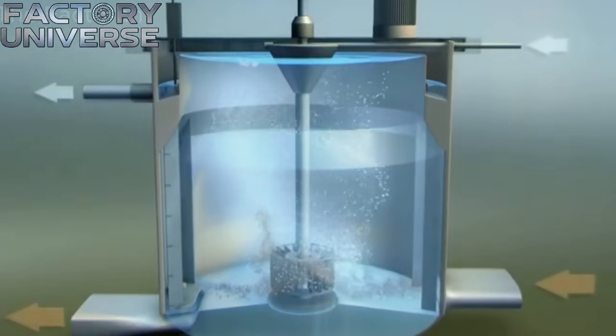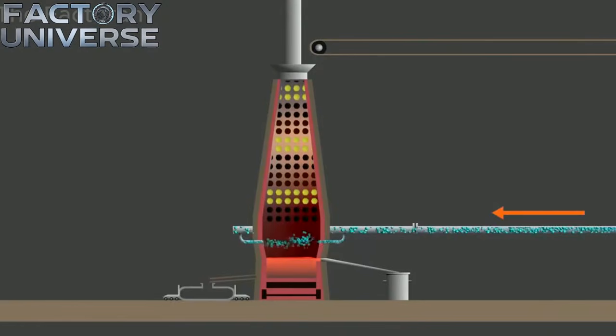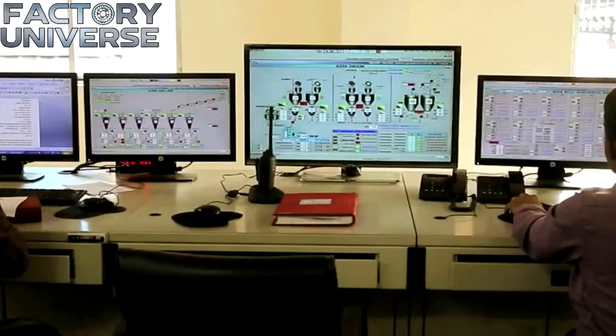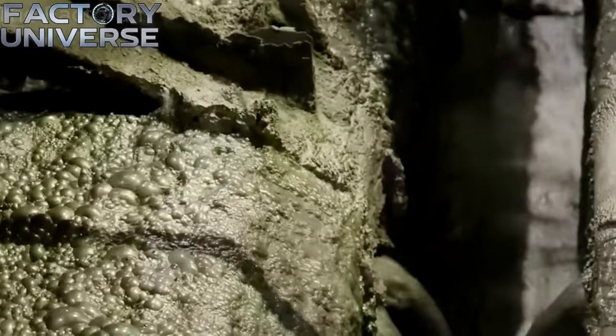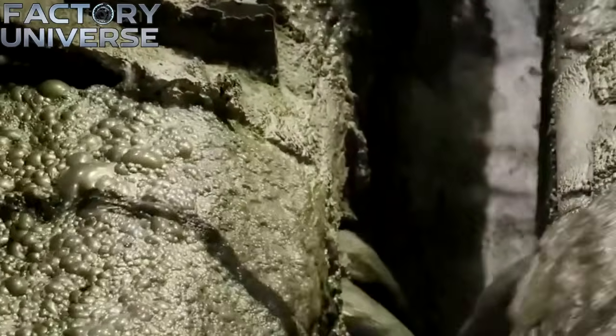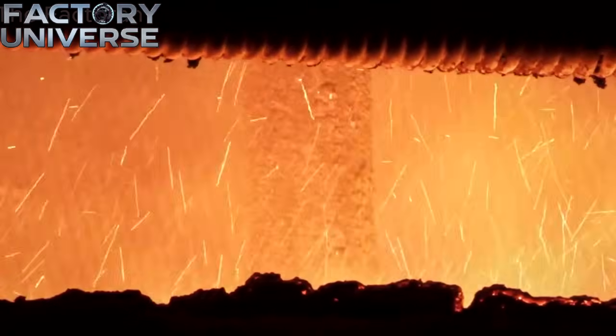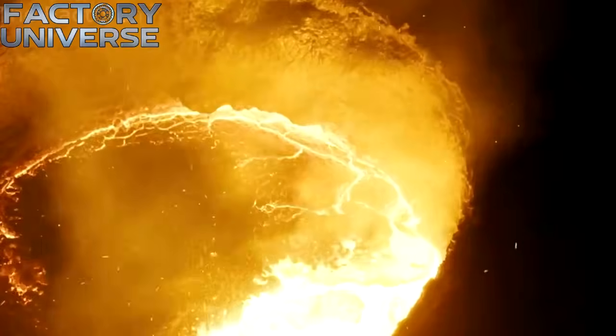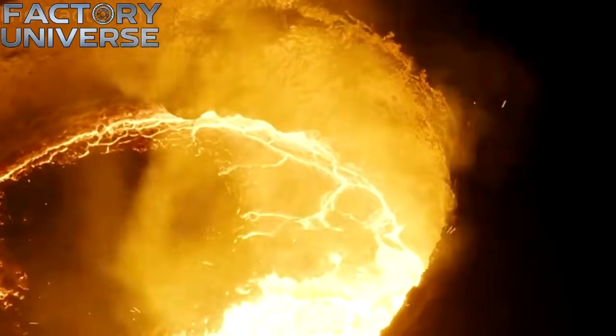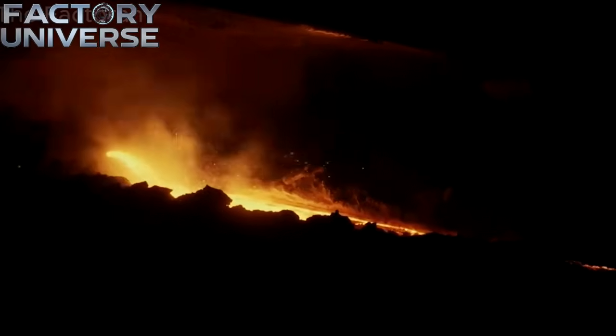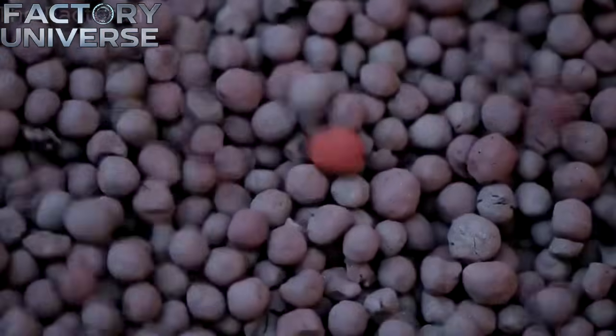Once the iron ore has been pelletized or sintered, it joins forces with the blazing hot coke fresh from the ovens. Layers of ore, coke, and limestone are charged in sequence at the top of the furnace. A powerful blast of hot air is injected from the base to sustain the reaction. Transition to the next level of chemical reduction occurs here. The coke ignites fiercely, releasing carbon monoxide that strips oxygen from the ore.